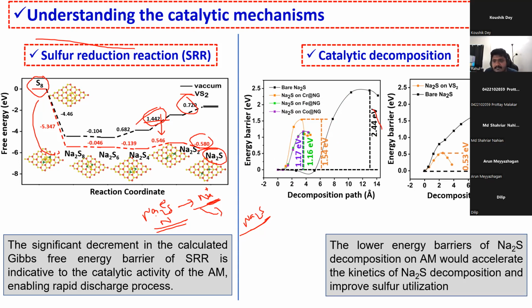But again, this is for the single atom catalyst. Again, when we use the VS2 based catalyst, you can see that this value from 1.17, this is the lowest value here. This value even reduced from 1.17 to 0.53. That means basically if we use a VS2 catalyst, it can do very good in the discharge process. It can easily convert the Na2S4 to Na2S, and during the charging, it can easily break the Na to S and send the sodium ion because it has a very low catalytic decomposition barrier.